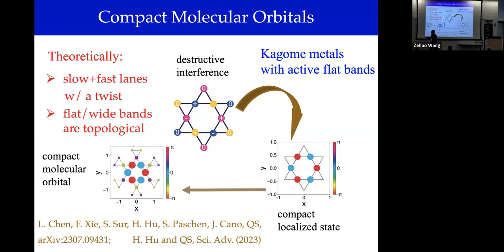It turns out there's some combination of this flat band and wide bands in which one can properly Wannierize it. And you can see that this is the most compact Wannier orbital. It's almost like this, except that you have tails decorating it. These tails are very important to make these compact molecular orbitals orthogonal to each other, coming from neighboring unit cells.